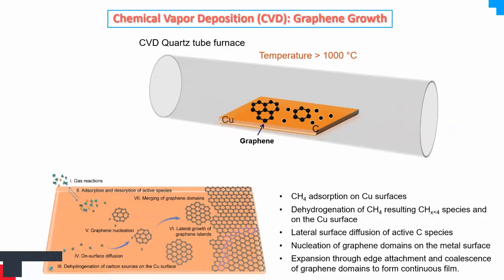Of course, there are different steps in graphene growth. First is adsorption, and then once adsorbed, it dissociates and removes the hydrogen. That step is called dehydrogenation. Then there is surface diffusion of the carbon species, and ultimately they stitch together to form a continuous sheet on the surface of the copper. So that's fundamentally how CVD works for graphene growth.